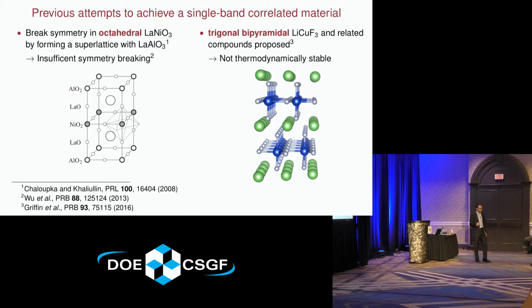A second theoretical proposal was to look at this distinct coordination called trigonal bipyramidal, which now is low enough symmetry that one in principle can achieve a one-band kind of model. Unfortunately, it was shown that these compounds are actually not thermodynamically stable. So it seems, even though they could be interesting, it's unclear if these could actually be synthesized. So in my approach, I'm going to take two things into consideration based on this. First of all, I'm going to avoid any high symmetry configurations. So I'm going to ignore anything that's, for example, octahedral or tetrahedral, because it seems like it's just too hard to break the symmetry from that high symmetry starting point. And secondly, I'm going to explicitly consider thermodynamics, so we have a high probability of actually being able to make anything that we discover.